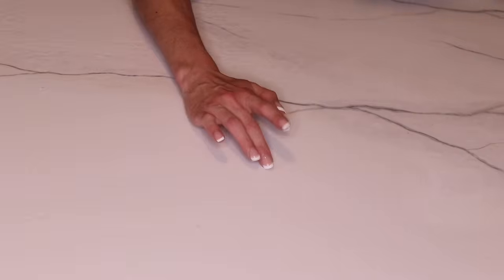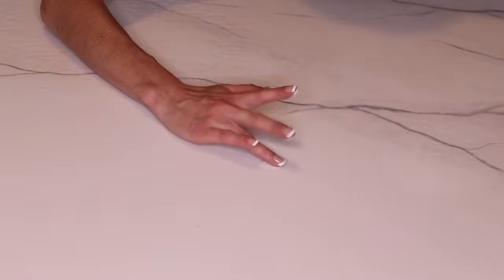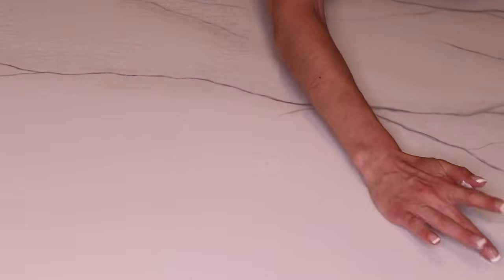So it was impossible. And I did end up having numerous bugs completely dry in the epoxy that I then dabbed a little bit of my white paint on, to make it blend in with the marbling I did. But it was definitely visible, and I was very unhappy about that part. One other major problem that I had when applying my epoxy is that I applied it to a level sheet of plywood, but the plywood itself was the low-grade plywood, so it had variances in the grain, and it wasn't flat. The top wasn't flat.